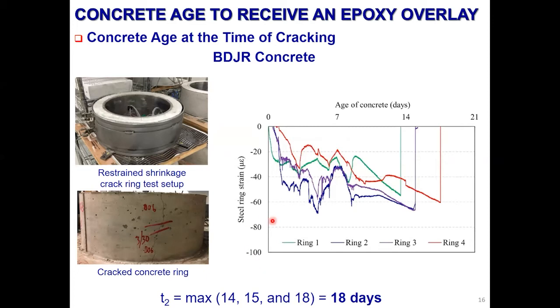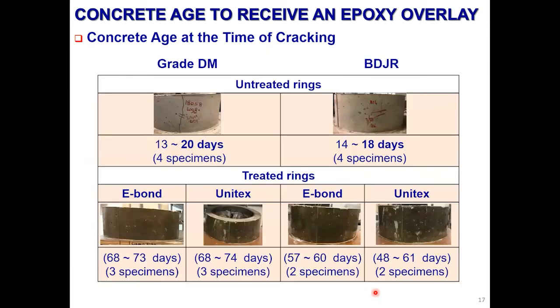So if you're going to apply an overlay on concrete with typical type 1 cement, then we need to wait at least 18 days according to laboratory conditions. Field conditions can be different. As I mentioned previously, someone can say, why don't we apply the overlay early, because it's going to trap moisture, enhance the strength and reduce the cracking potential. Yes, cracking potential will be reduced, but it can't prevent cracking, because we used overlays on shrinkage rings and they started cracking. Yes, it took longer, but they still cracked.